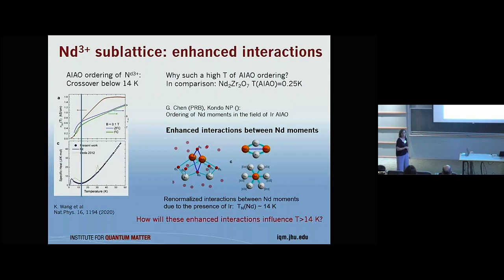Thank you. I had another question. I don't quite understand why you've chosen 14 Kelvin as the crossover temperature for neodymium ordering. It's well above this broad peak that you show in the specific heat. We already discussed the high energy scale of the disappearing excitation, but this is already a high temperature scale compared to this broad peak in the specific heat. So, if I understand you right, why we chose this particular one? Below it, there's a broad peak in the specific heat at 1 or 2 Kelvin. We chose it as an upturn of the specific heat for this particular sample. And there is multiple evidence that this peak itself is due to this crossover ordering of neodymium, all in, all out.